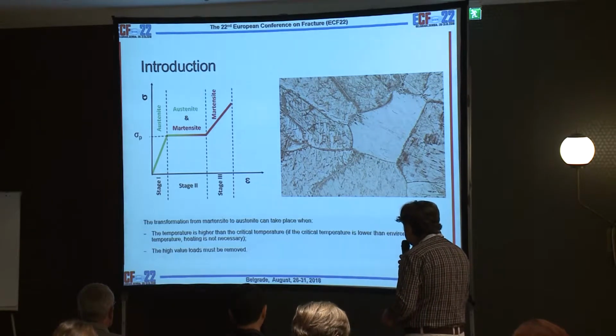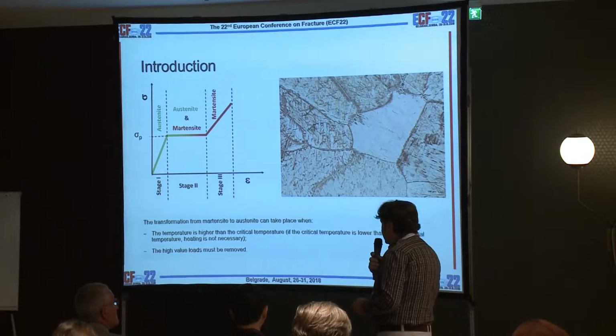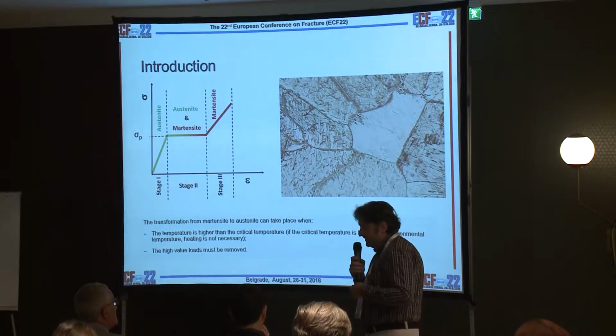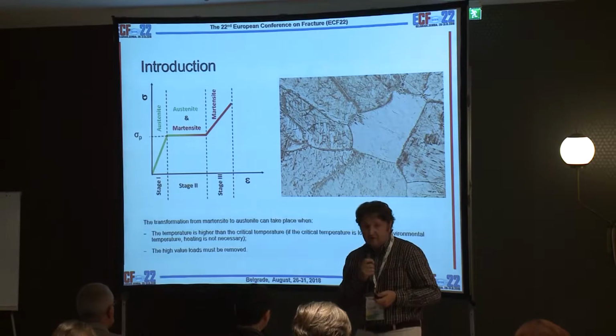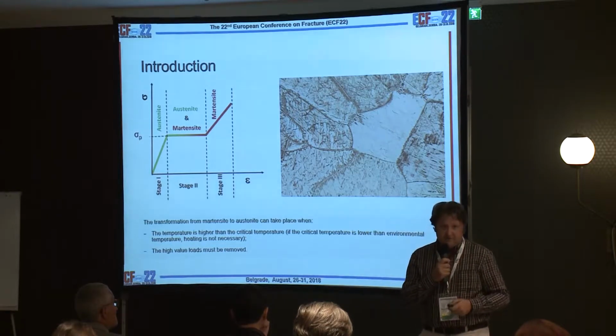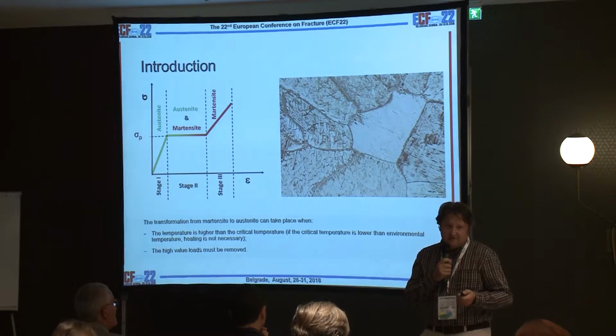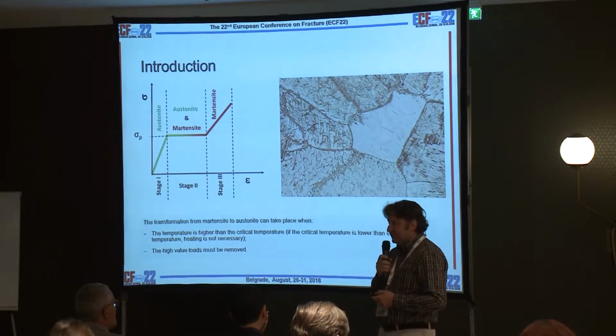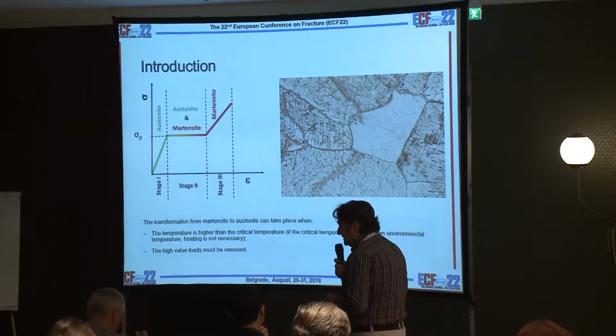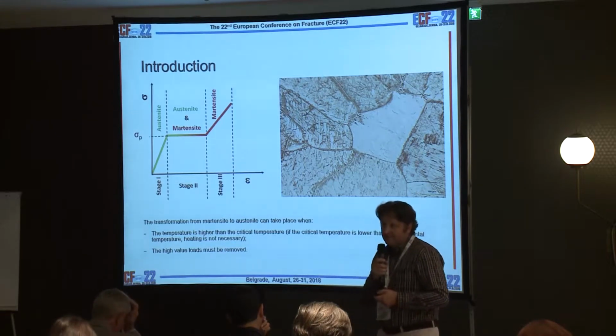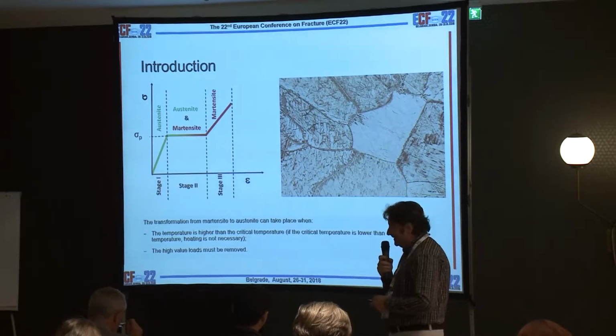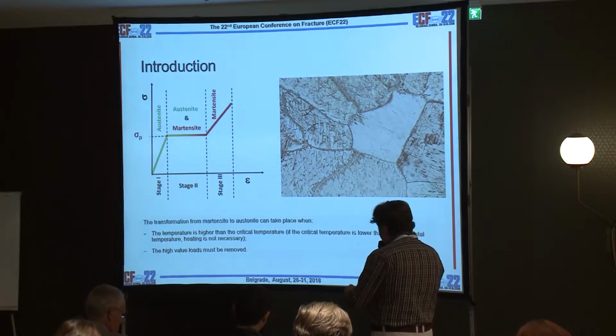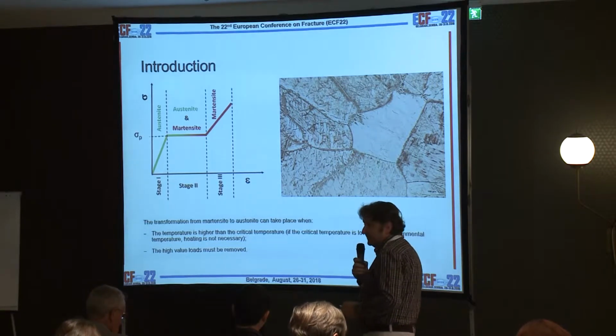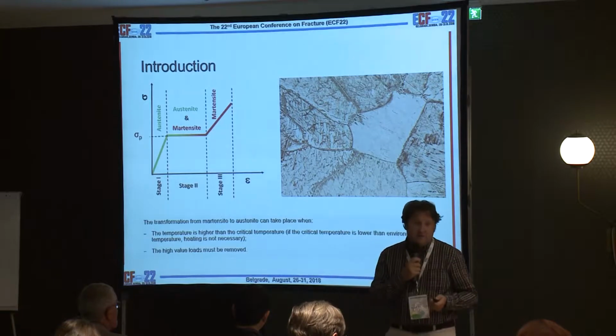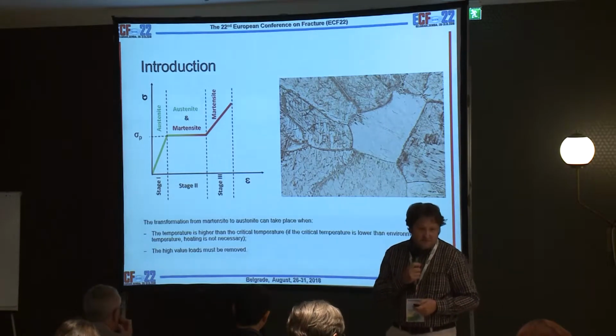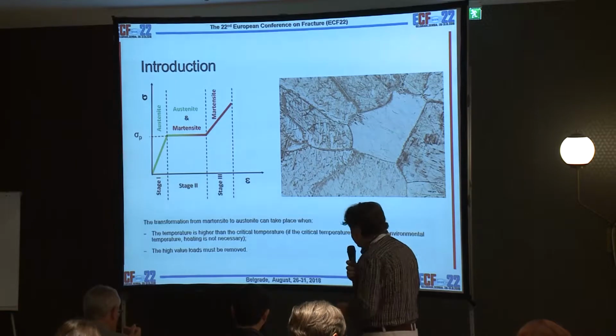In the second case, we have a critical temperature of the material less than the environment temperature. In this case, heating is not necessary to recover the transformation, and the macro behavior seems like a fully elastic transformation, but the relationship between sigma and epsilon is not linear. In this case, we talk about pseudo-elastic transformation. This is the case of our material.